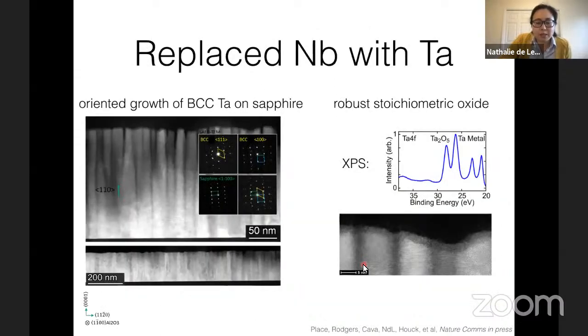The second piece, and this was really Bob Cava's suggestion, was, he said, why are you working with niobium at all? Tantalum has a perfectly fine superconducting critical temperature, and it has much, much nicer oxides. So what we were able to do was just replace niobium with tantalum metal. It turns out that you can actually get really nice oriented growth of the correct phase of tantalum on sapphire. So the tricky thing about tantalum is that if you just naively grow a thin film, you get a much lower TC superconductor, you get the beta phase. But what you can do is just heat up the substrate and you get BCC tantalum, which is the alpha phase.